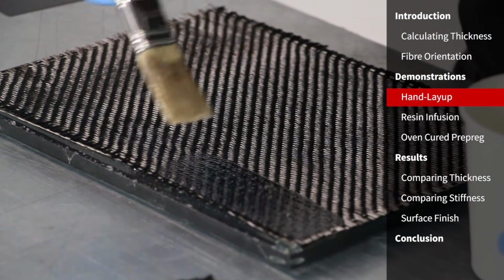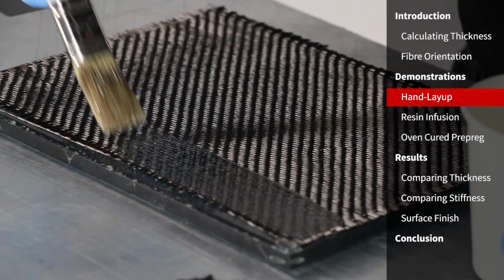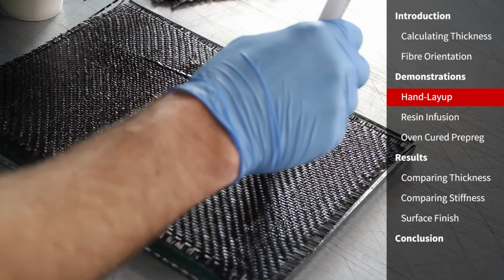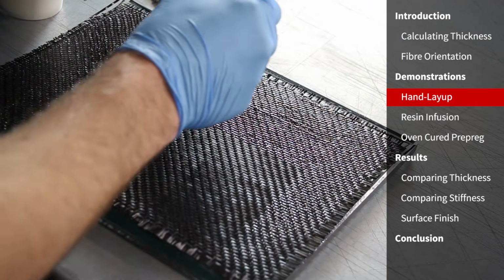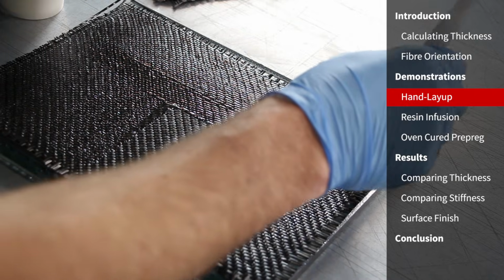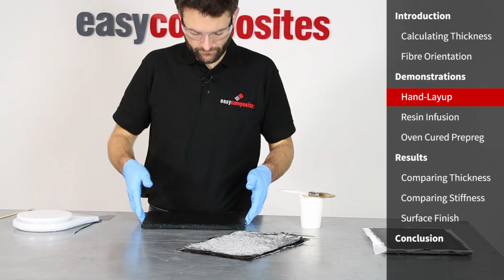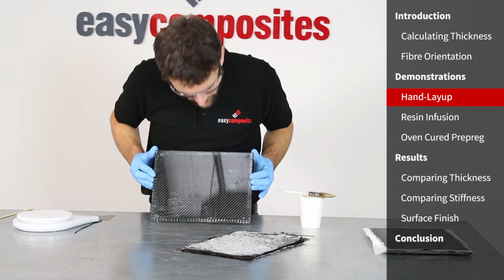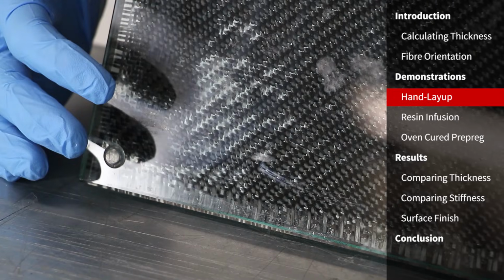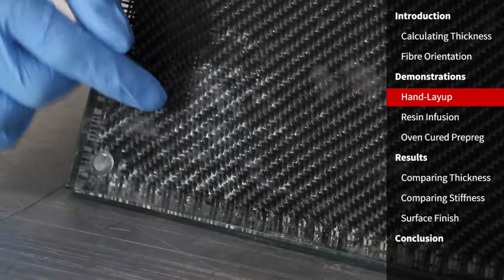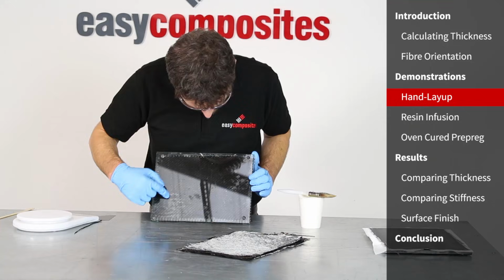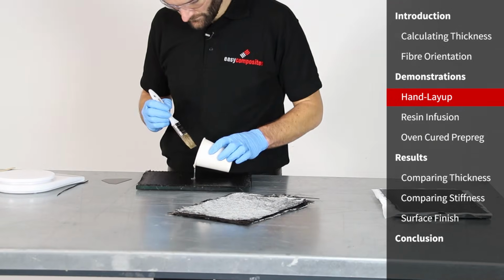Being another wet lay sheet example, we are following the same process. We've started by adding the resin first to the surface, and then our layer of 200 gram 2/2 twill carbon has gone down first. The first layer with any carbon fibre sheet is always going to be cosmetically the critical one, so we're having a look again on the underside, checking for any dry patches. You can see we've got some dry areas here, there's some other at the top.